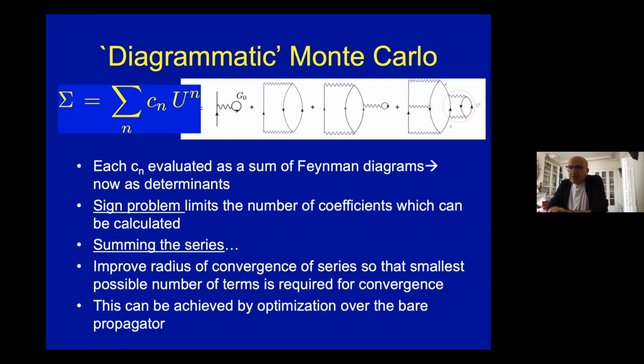So in a nutshell, this Diagrammatic Monte Carlo method consists in generating the perturbation series. This slide here would be for the traditional DiagMC method, but now you have to think about it as generating determinants. What limits the applicability of this method is that at some point a sign problem pops up, which limits the number of coefficients in the series that you can calculate. Importantly, you also have to resum this series, and make sure that the radius of convergence of the series can be properly managed so that you can reach convergence at the value of U you are interested in. These are basically the two questions, generating the coefficients and summing the series, that are the key challenges in this method.